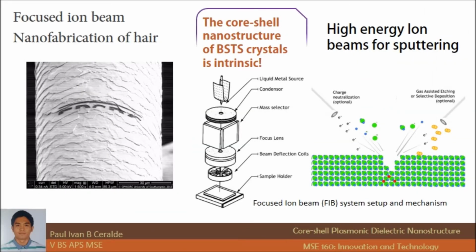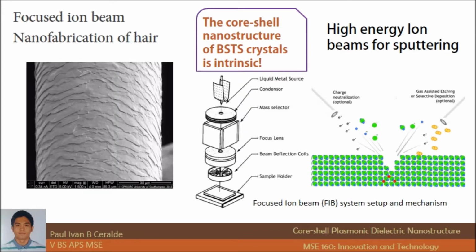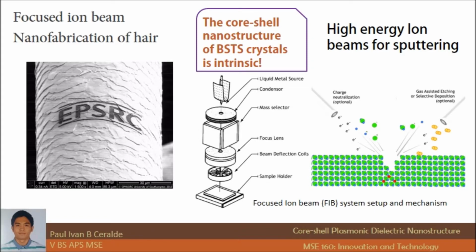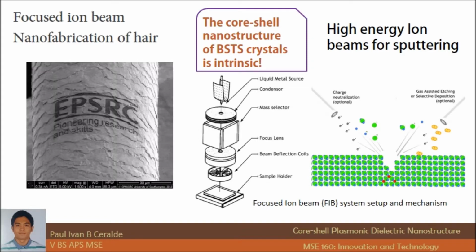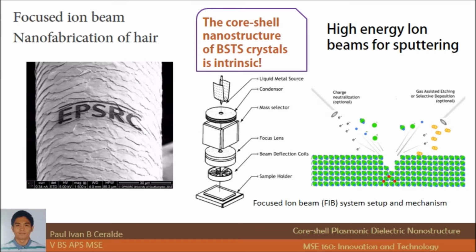The BSTS crystals used in the study display such properties intrinsically. The material possesses a core-shell topological insulator structure that conducts photon-plasmon interaction, resulting in plasmon polaritons. The crystals were nanofabricated using a focused ion beam system, which uses the same principle as scanning electron microscopes, but with finely focused high-energy ions instead of electrons.